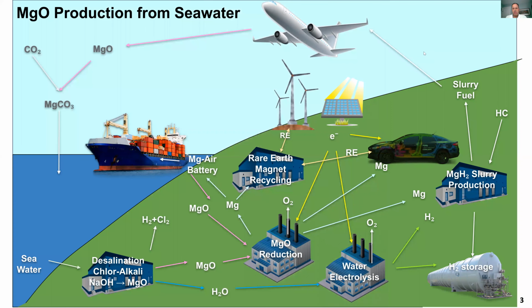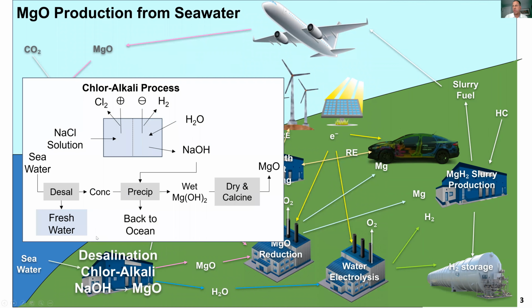So this is a layout of the overall vision. I'll walk through it and explain each part of it. We begin with seawater and use membrane desalination, as I mentioned, to produce fresh water. We take the remaining concentrate and react it with sodium hydroxide from the chloralkali process to precipitate out magnesium hydroxide, which we then dry and calcine to produce magnesium oxide.